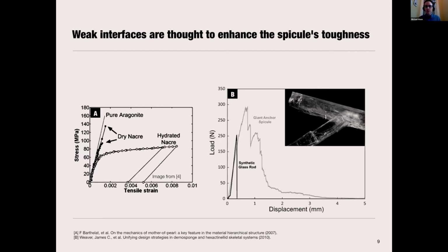And also, when they did 3-point bending tests on some related species, if you look in subfigure B, the gray curve is from a different species of sponge that also has layers, albeit much more of them, about 500 layers in this case, they have this jagged force displacement response, which they attributed to a progressive failure of the layers and an increase in energy dissipation, and that the layers were providing some mechanical benefit to the animal by enhancing the energy dissipated during failure.